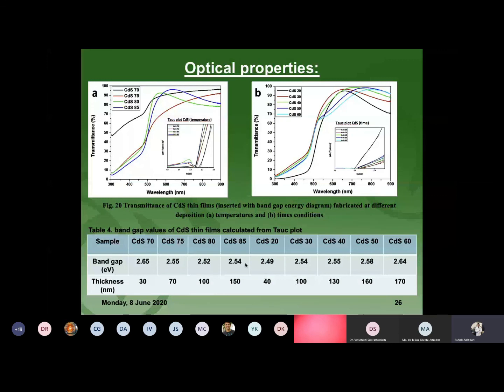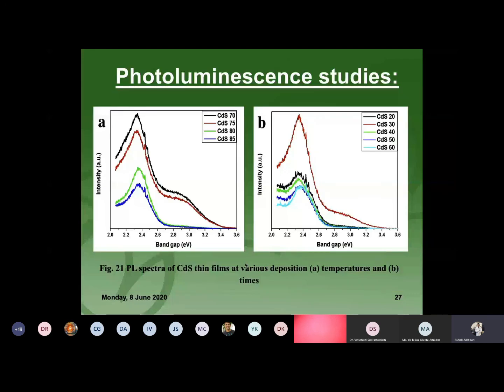For further quality assessment of the films, we checked the photoluminescence and observed the major peak in the range of 2.2 to 2.6 electron volts, which is the green emission band. The presence of this green emission band signifies better crystallinity of the films with minimum defect density.